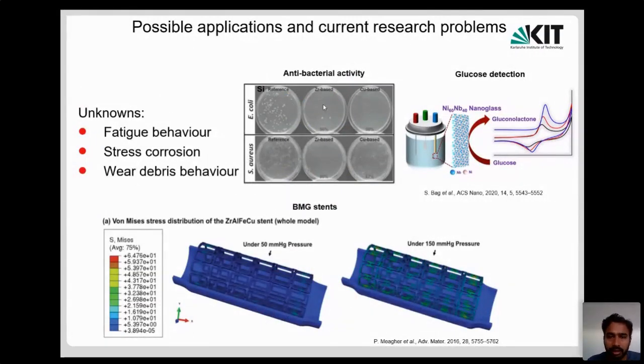So they have taken these kinds of glasses. You can see zirconium-based and copper-based glasses here, and they have put some bacteria, and the silicon is the reference here. You can see on the silicon reference the bacteria grow quite well, but on the zirconium-based and copper-based glasses, the bacteria grew comparatively very little. And this indicates that the glasses can be used as some kind of antibacterial coatings, which is one area of research going on this way.